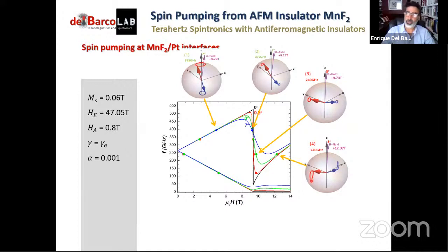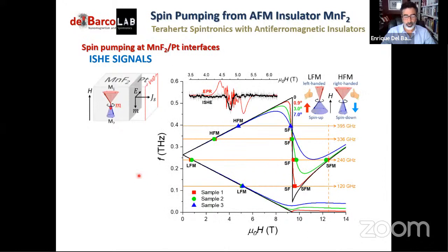All right, so beyond spectroscopy measurements, we can also report the electronic measurements, right? So the electric voltage that we get out of the two wires attached to the sample. And this is the black line here in comparison with the EPR, the spectroscopy feature. Now, don't be misled by the shape of this spectroscopy feature. It's really, really noisy. And the reason for that is that the samples are big enough to basically distort, saturate the sample probe. And that's why we're not able to define very nicely the spectroscopy feature as we would like.